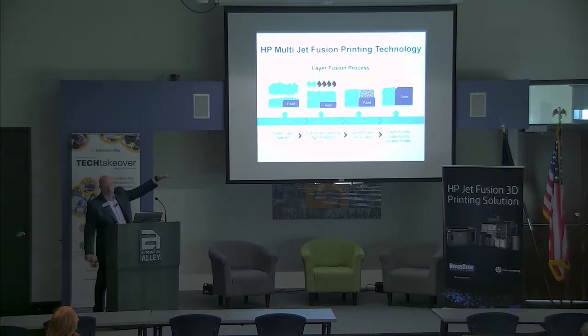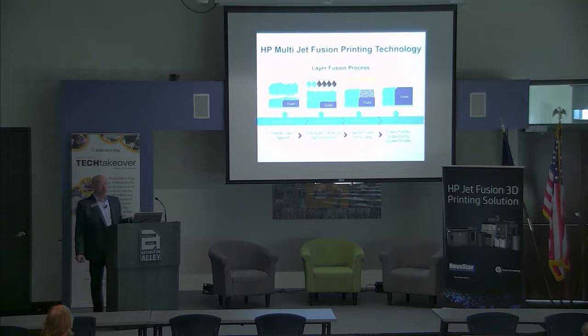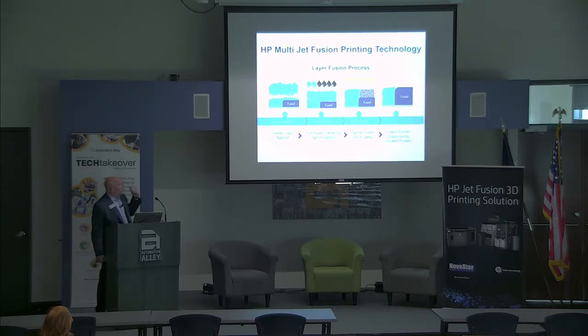Once the fusing agent and the detail agent are laid down, we pass over with a heat lamp. And where the fusing agent has been applied, the parts fuse. And where the detail agent has been applied, it inhibits fusing so that it does not fuse. Once the heat lamp has passed over it, you have that layer properly fused or unfused where you don't want part. And it just does this over and over again in 80 micron layers to build up the part.